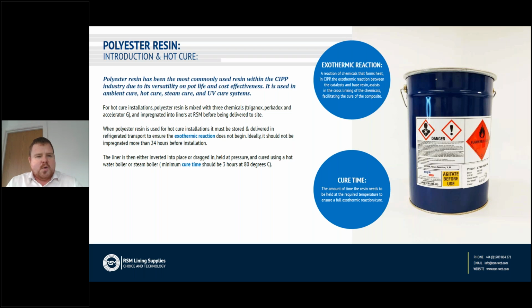Initially, we're going to look at the hot cure process. The hot cure process involves mixing a polyester resin, usually a filled resin, as it holds in the liner material much better than an unfilled material. It also makes the material more cost effective. For hot cure installations, polyester resin is mixed with specific catalysts and accelerators, and it is impregnated in a factory setting in a controlled environment, usually into a needle felt liner. The needle felt liner can be glass reinforced. The needle felt liner is then stored in refrigerated transport until the liner is due to be installed on site.